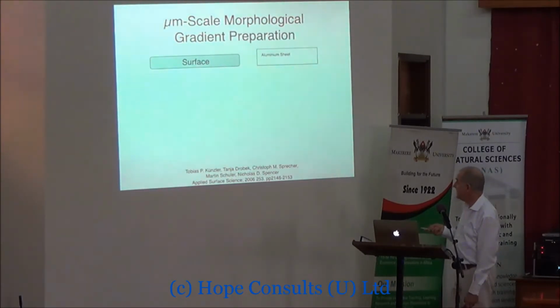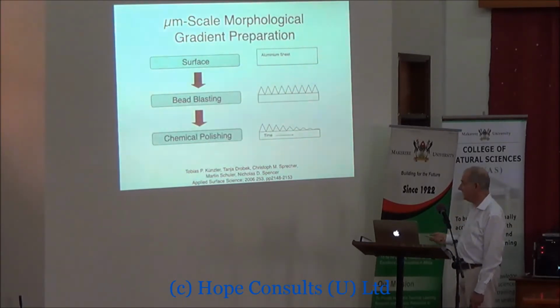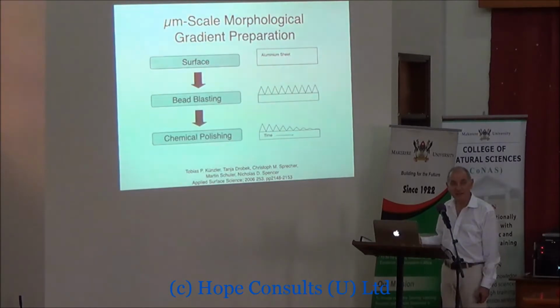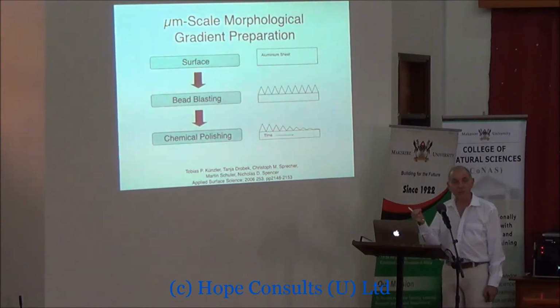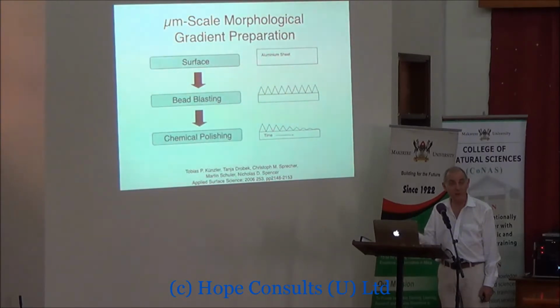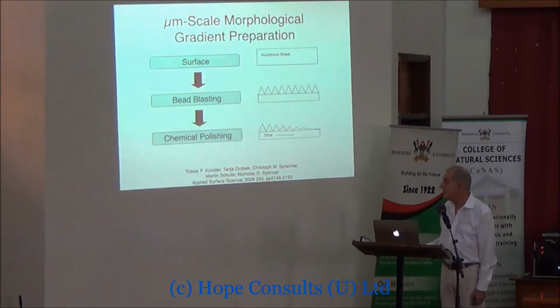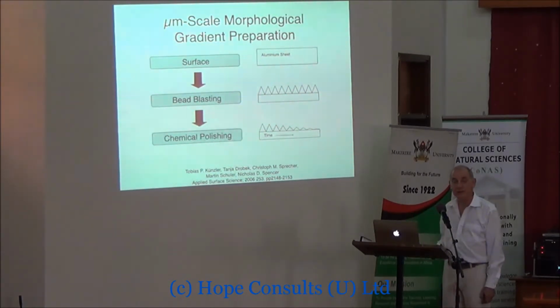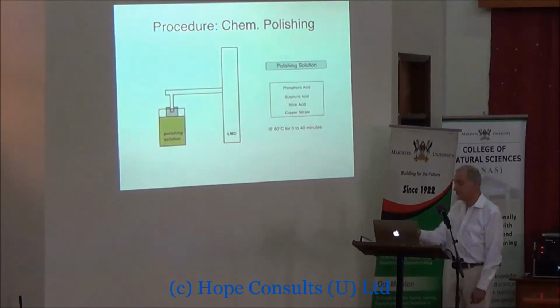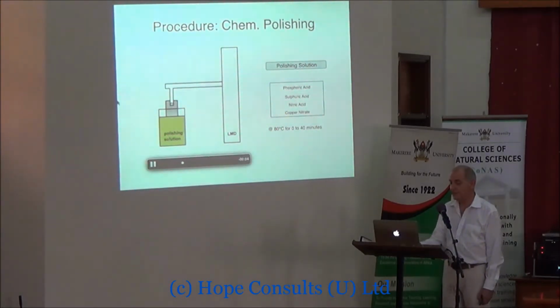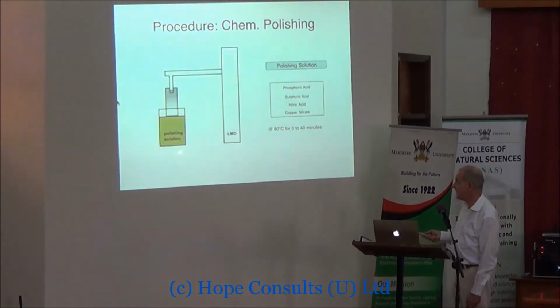And the way we did that first was we took an aluminium sheet and we sandblasted it. So just a regular sandblaster that you find in the machine shop to make it rough on the micrometer scale. But then we polished it using our dipping machine again. We dipped it into a chemical polishing solution, and because the chemical polishing has a certain time dependence, the longer it's in there, the more polished it gets, then by dipping it slowly, you can make one end more polished than the other. And that's what we did. We just dipped our sample into the chemical polishing solution. So again, it was using the same apparatus, withdrawing it actually this time from the polishing solution, and this end was more polished than this end.